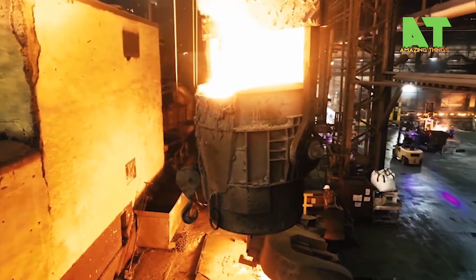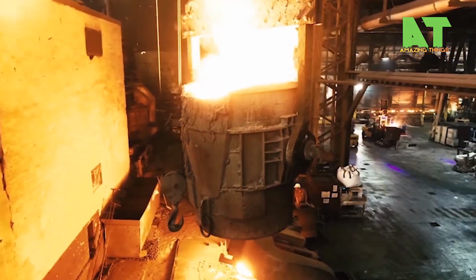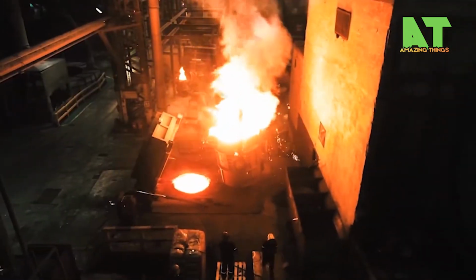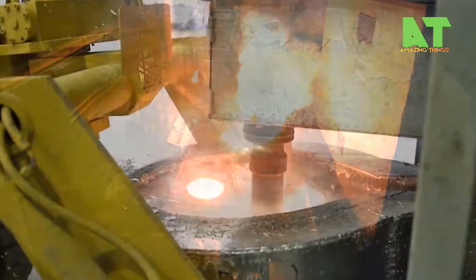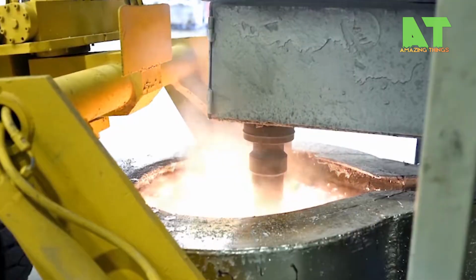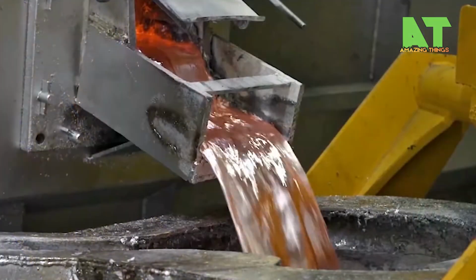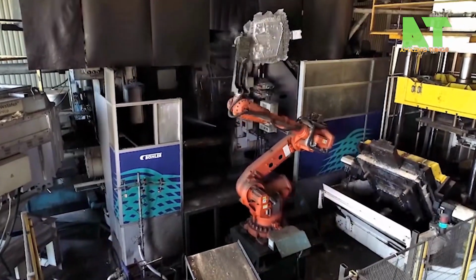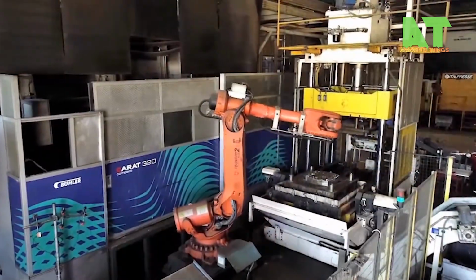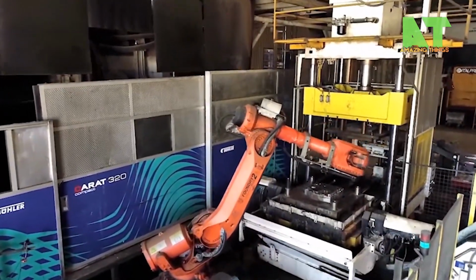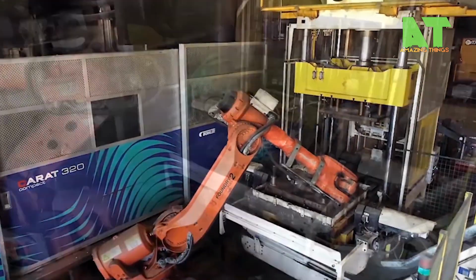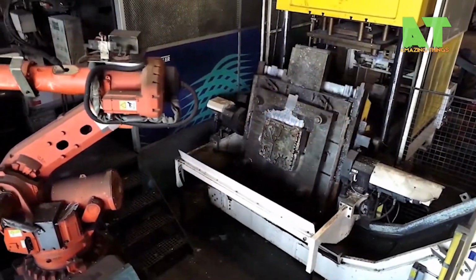The dies themselves are precision machined to match the final gear geometry closely, so material is used efficiently and grain flow follows the shape of the part, which dramatically improves strength compared to machined-from-bar alternatives. After forming, the gear blanks go through machining, hobbing, shaping, or grinding to cut the final tooth profile to micron-level accuracy. Then heat treatment and surface finishing bring the component to final specification.